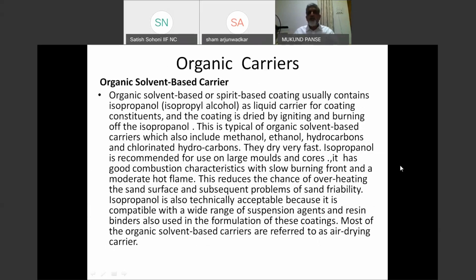These are mainly isopropanol, that is alcohol base. The coating has to be dried by igniting or heating. The typical organic solvent carriers also include methanol, ethanol, hydrocarbon, chlorinated hydrocarbon, etc. They dry very fast. Isopropanol is recommended for use on large moulds and cores.